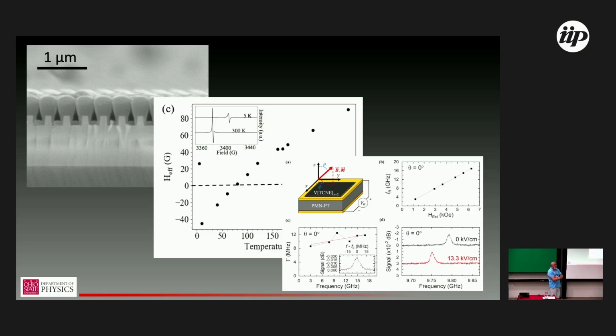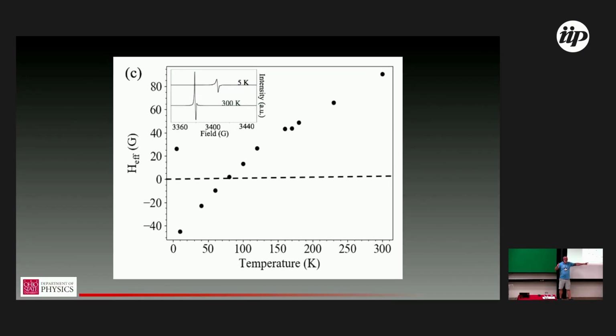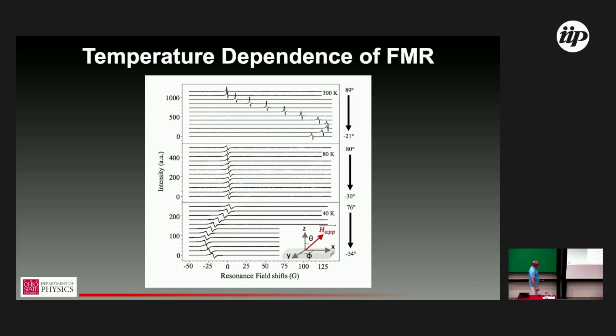So giving you a temperature control of the uniaxial parameters, would you say that at low temperatures this has a perpendicular magnetic anisotropy, so it goes out of plane if you're not forcing it by an external magnetic field? Yeah, it absolutely does. Sorry, it took me a second to translate that, but this negative H effective means out of plane is the easy axis. Thank you. And so you can also see that here, as we rotate the field, we get a shift to lower field for the resonance.